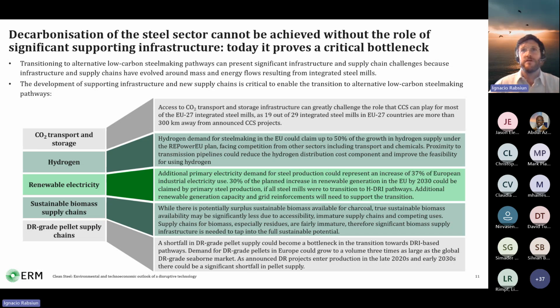In the case of hydrogen, if all of the 29 sites transition to hydrogen-based direct reduction of iron, not saying that that will be the case, but it's a scenario of maximum demand, they would claim up to 50% of the growth in hydrogen supply that is envisioned under the REPowerEU plan. And that means that they will face lots of competition from other sectors like the production of synthetic fuels or low carbon chemicals.